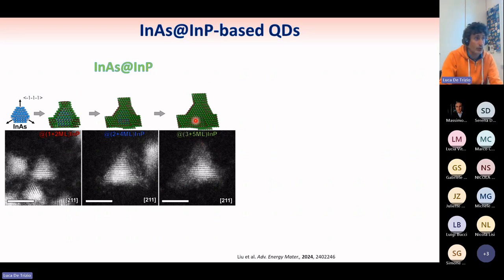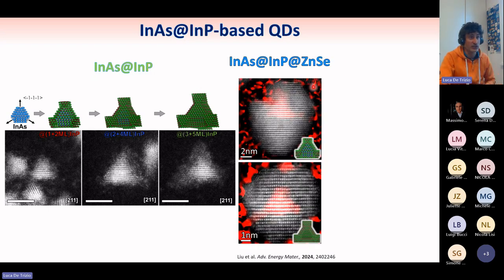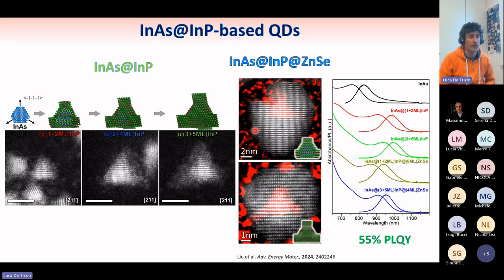which can be also called tetrapod because of the 4 pods that you can see in the sketch. We covered them with a zinc selenide shell to form these complex heterostructures, and eventually we got a bright emissive core shell structure in this case, with emission down to 1000 nanometer. So we were the first having such bright emission with these indium arsenide and indium phosphide based compounds.